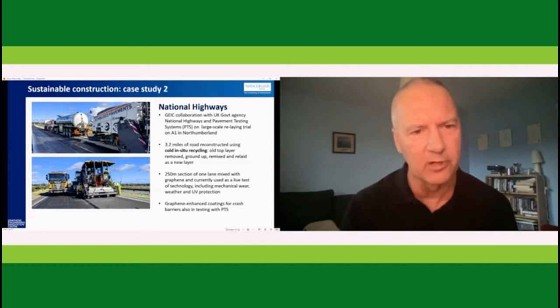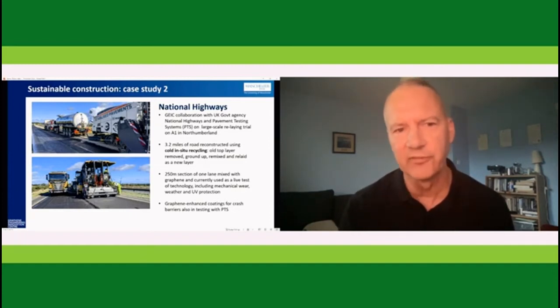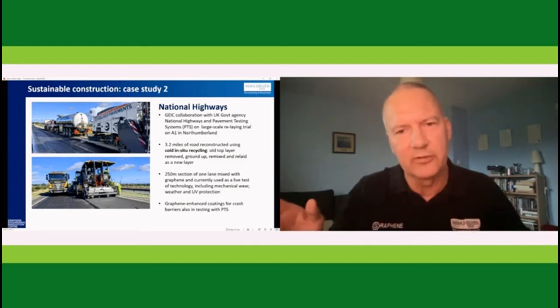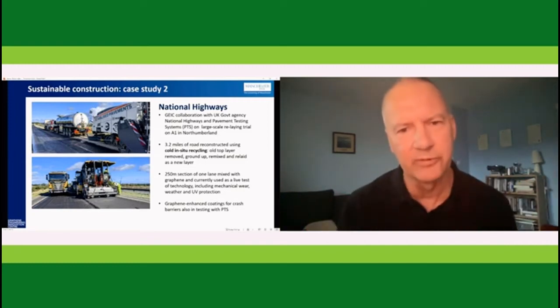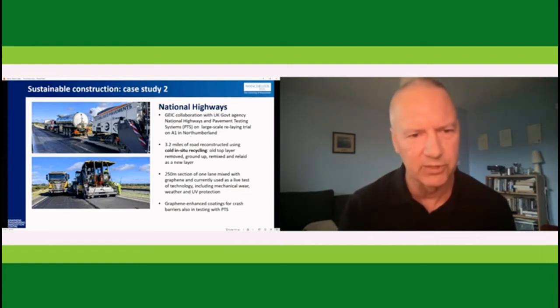benefit the road network. So what we did with National Highways is we did a section of, as well as the testing, we did a section of a live road trial. So it's a section of the A1 main road in the north of the UK. And it's several miles of total recycled aggregate, but on one section of that, we've done a graphene enhanced section. So we can compare that in performance with the baseline solution. And again, initial results look promising, but we're now doing those tests and the evaluation as we talk.